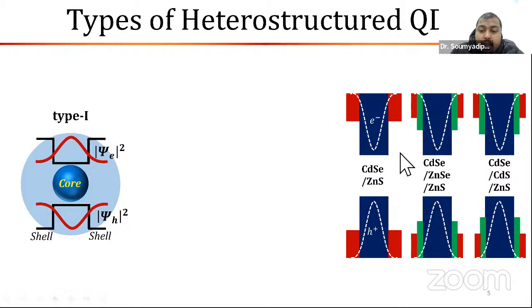And here you can see we can have different kinds of shell structure: zinc sulfide, zinc selenide, or cadmium sulfide. Every shell has a different purpose to serve. First of all, if we coat with zinc sulfide, it prevents the exciton leakage, and therefore the quantum yield also increases. For zinc selenide, the valence band leads to a better exciton confinement, and therefore the quantum yield increases more than with zinc sulfide.